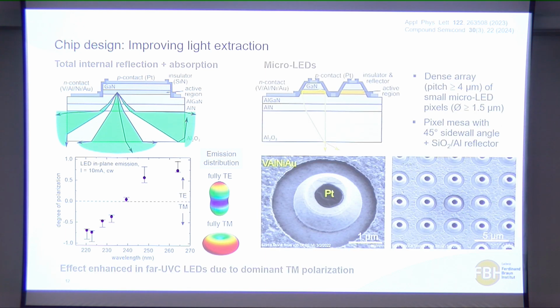And to do that, what we are using is micro-pixel LEDs. So basically, we are reducing the size of the LED to a much smaller size, a size of 1.5 microns. Each of these LEDs, you could consider them to be micro-pixels with an array of 4 microns. And then we have covered the system with silicon oxide sidewalls, which are 45 degrees, and then we put an aluminium reflector on the system.